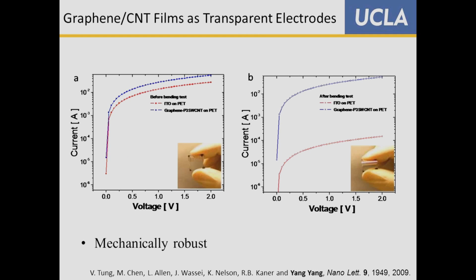Well, we took indium tin oxide on plastic, which is polyethylene terephthalate, like a Coke bottle, this kind of plastic. And we took our graphene and we mixed it with carbon nanotubes. And we made a material that's equally conductive. Then we bent them each 10 times.